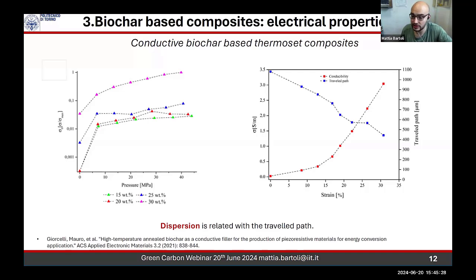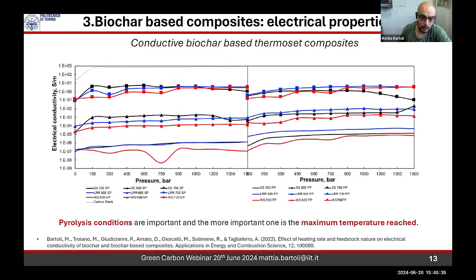Carbon black is the reference point for any kind of composite study, but in this case it is outplayed. And here we are going to one of our recent investigations. It's a quite comprehensive one. We proved that temperature matters, and the threshold of the temperature was around 1000 degrees. We proved that the structure matters. Particles with micron size are better than nanometric particles, which was unexpected.